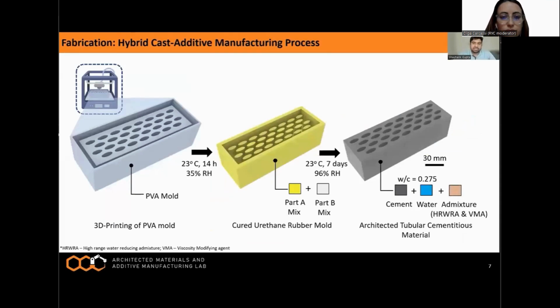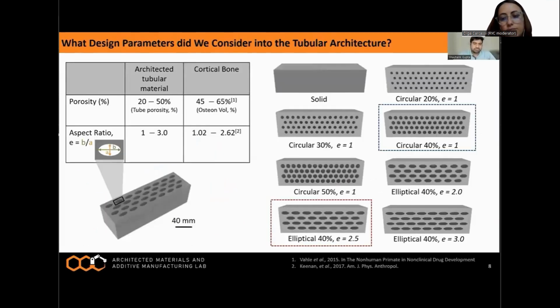Another method that we can use is a hybrid process in which we 3D print a PVA mold, then cast urethane rubber into it and demold the PVA to make this urethane rubber mold. Then we use this urethane rubber mold to cast the cement paste. This method enables direct formation of tubular system in cementitious material. And this is also the approach that we have used for what I will be presenting today.